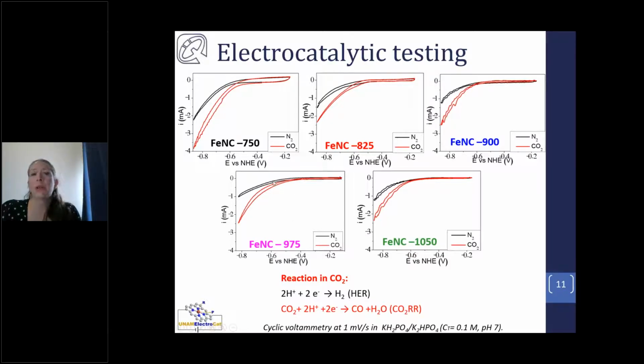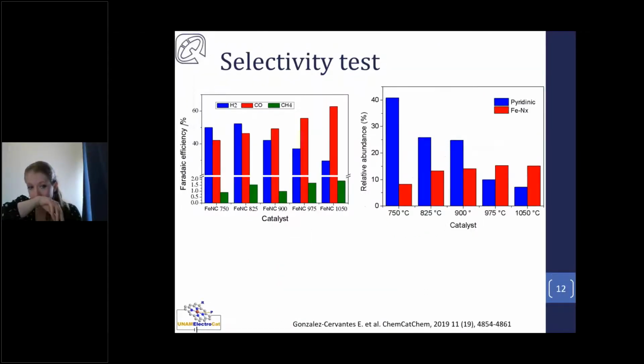To figure out if this current is attributed to CO2 reduction or hydrogen evolution reaction and which products we are forming during this process, we did some product quantification, and what we are showing here is the product quantification after CO2 electrolysis. And we did see that the synthesis temperature also affects the selectivity of the process. What we observed is that when we prepare the catalyst at a higher temperature, we reduce the selectivity towards hydrogen evolution, and we enhance the selectivity for the production of carbon-based products, namely CO and methane. We want to understand this in terms of the active sites presence, and what we see is that this increase of nitrogen coordinated to metal and the decrease of pyridinic results in a higher selectivity towards CO2 reduction.